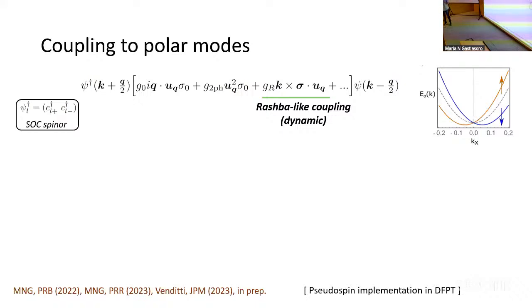I think it's much more interesting to stay at linear order in U, so still linear order in this polar mode. But then by symmetry, you can also have this thing, which involves k of the electrons, so the momentum of the electrons, and sigma of the electrons. So this is something that is a dipole, that is non-magnetic. It's just an electric dipole coupling to the spin, and this is very strange. It's Rashba-like in the sense that you can think that you have these electrons where the spins are degenerate, and when you activate this polar mode, it sort of creates this Rashba-like split, but this is dynamic.